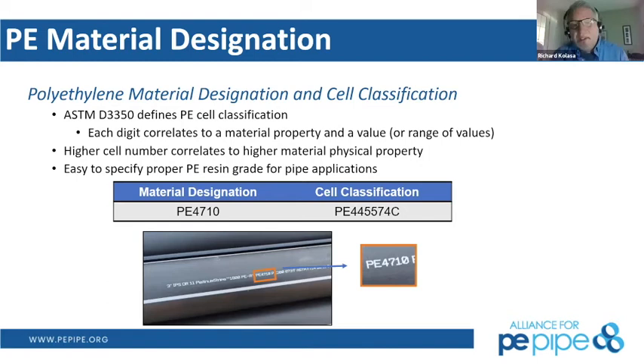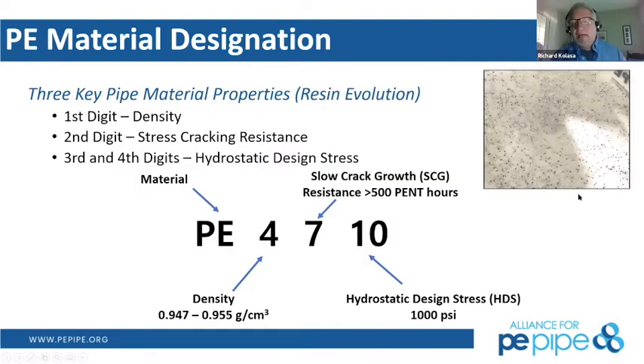If you go to the next slide, the cell classification, the long term, is all of those items that you require in design. The short term, which you'll always see on the pipe print line, is the material type, the density class, which in this particular case 4 is 0.947 to 0.955, so just below 1. That means the product floats. Then also the slow crack growth performance, and the reason slow crack growth is so important is because it's changed over the last 10 years, or these 2 generations of products. It was pretty good in the 3408s and 3608s, but it's really outstanding now in the 4710s.